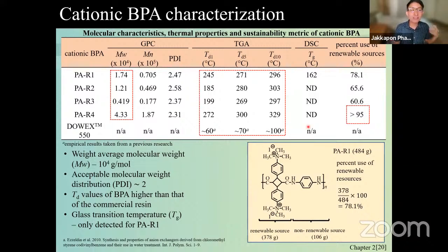in terms of thermal properties and molecular characteristics. I use GPC, TGA, and DSC to see, and you can see that the TGA is quite good here, about 300 degrees Celsius for Td10, compared to Dowex here.